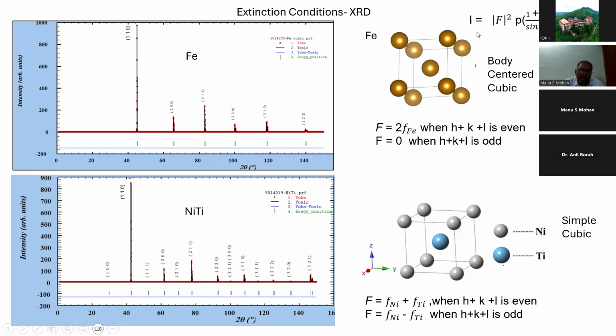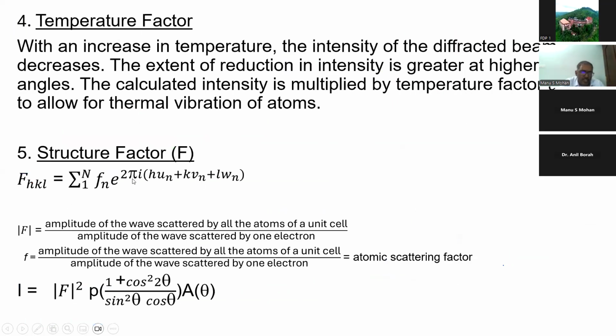So when you substitute in this expression, F equals small f into exponential 2 pi I into hu plus kv plus Lw, you get F equals 2fe when h plus k plus L is even, and F equals 0 when h plus k plus L is odd. Coming back to that expression: h, k, L basically represent the Miller indices of the planes, whereas u, v, w denote the coordinates of the atoms.